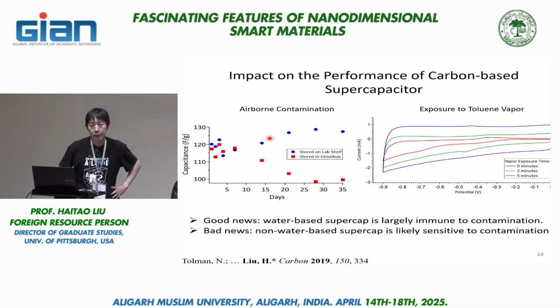And what is happening here, we find, is because those materials are so hydrophilic, because they have a lot of oxygen functional groups on their surface. They're very hydrophilic, so they get covered by water quickly if you expose them to lab air. So the water actually protects them from being contaminated by hydrocarbon.